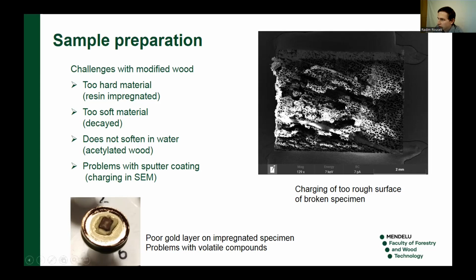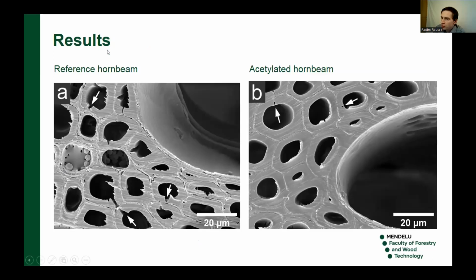Also, in case of rough surface, if the sample is smaller, the charging is lower. In this case, the sample is about 2 by 2 millimeters and about 0.6 millimeters thick. The layer of gold was poor, but it was sufficient to make some images. Now, I will show you some results from my electron microscopy.